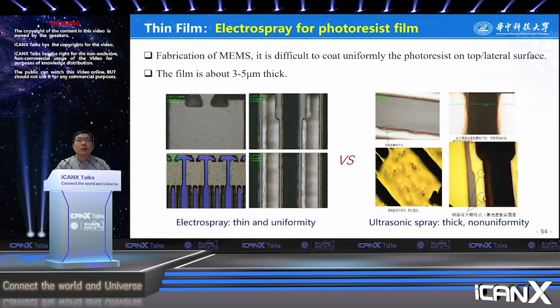The fabrication of MEMS, such as the crystal oscillator, makes it difficult to coat the photoresist uniformly on the top and the lateral surface. The left figure shows the photoresist film deposited by this process. It's very uniform, and at the same time, the lateral surface is also coated by the photoresist film.